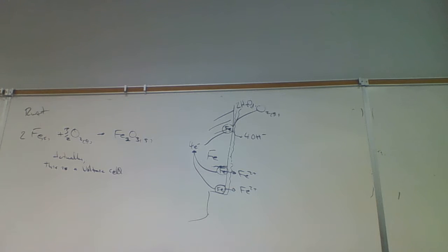In Petri dish B, they took a nail and they folded it in half. If they fold it in half, you can create lots of defects here and make that susceptible to corrosion. So what's susceptible to corrosion are the hammered ends and the corner here. And so again, here we have two cathodes and 3 anodes. That's because the defects in the structure are going to cause the iron to have a higher oxidation potential. It'll be easier to oxidize.